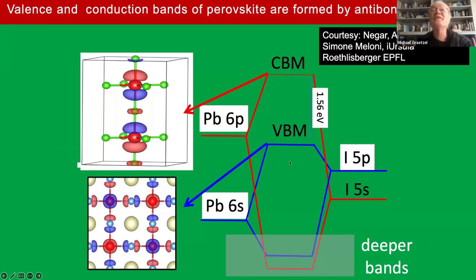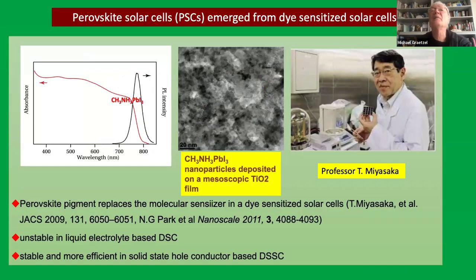And so when you break, say, a lead iodide bond, the formula is MAPbI3, if you break that bond, it actually stabilizes the system. While in silicon, if you break a silicon-silicon bond, you would make a very deleterious defect in the middle of the band gap.